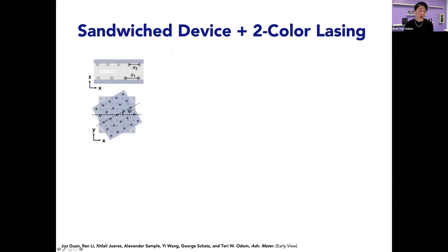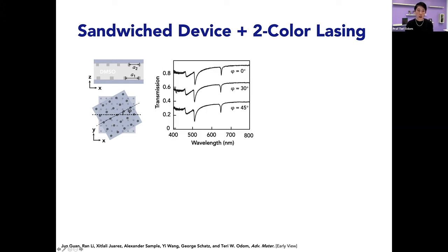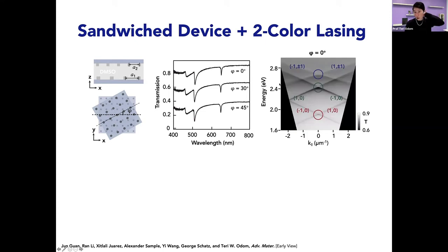Okay, then we decided, well, can we sandwich these lattices together, and what do their properties look like? The bottom lattice and the top lattice have different lattice spacings, the same ones that I introduced earlier. And you can see that regardless of the twist angle, if you will, in terms of the linear optical properties, they remain the same. So they look nice. You see these 3 SLRs. And if we look at what the modes look like, this is the dispersion diagram. You can see this is the gamma point here for the red SLR, gamma point for the green, and the gamma point for the blue SLR.